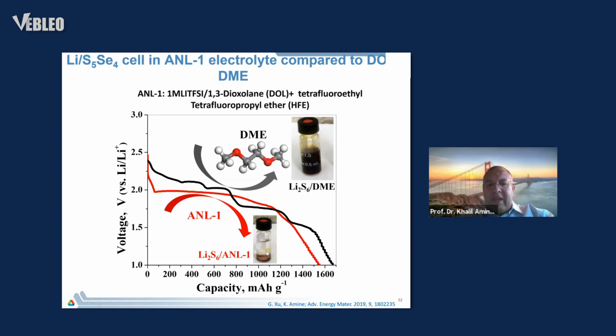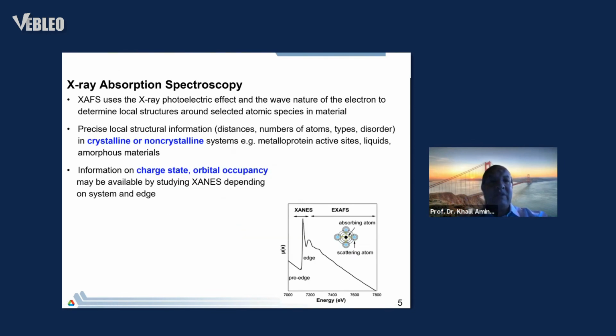We also look at the electrolyte color. If you have an ether base, you have discoloration. That is a sign of dissolution. We don't have it, but coloration is not really a scientific way to make that judgment. So we developed a new technique at Argonne using the Advanced Photon Source, using XAS, X-ray absorption spectroscopy. XAS is a good technique because it can probe the oxidation state of materials either in the amorphous phase, crystalline phase, or in a liquid phase. At the APS, you can run one spectrum within 1 minute.